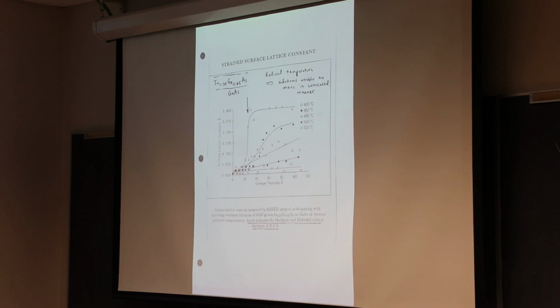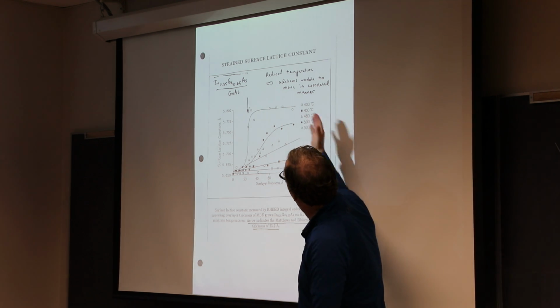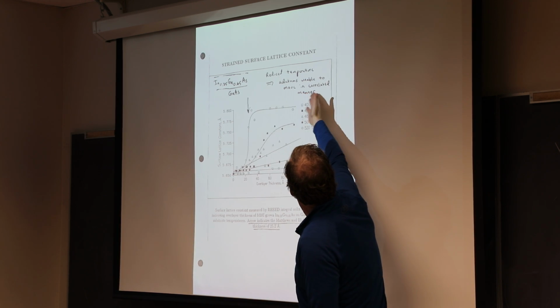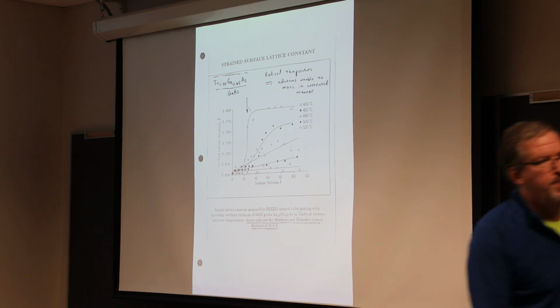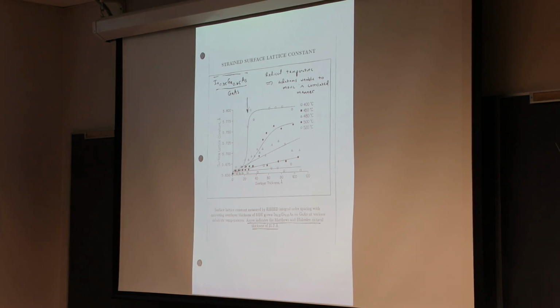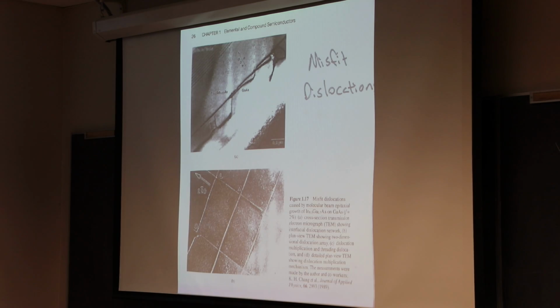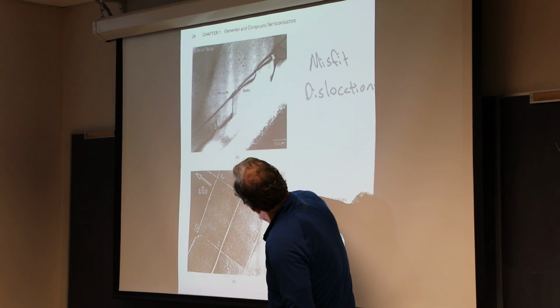This is showing how I can look at this. This is more information than you need. It shows me that I can inspect this at the atomic level. And remember, this showed you that misfit dislocation generation is not fiction. This is something I actually observed from first principles in the reactor during the growth. And you see the lattice constant change. So, here's what the misfit dislocations look like from the side. This is what they look like from the top.